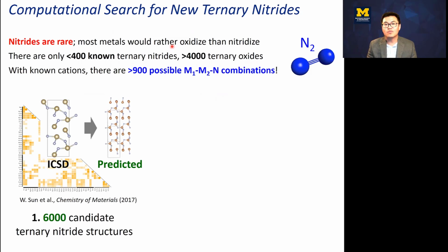Now, we use a pretty routine method in computational material science now for materials discovery. It's based on this idea of structure prediction. And the way that we do that is we first take all the known prototype structures in the ternary nitrides, and then we do rational chemical substitutions on them to extend the known ternary nitrides to a much broader composition space. Okay, and so what I mean by that is I might replace lithium with sodium, or iron with manganese, chemically meaningful substitutions, which we actually data mine, and it's discussed in this paper right here.